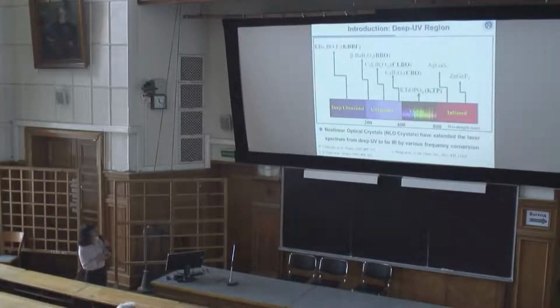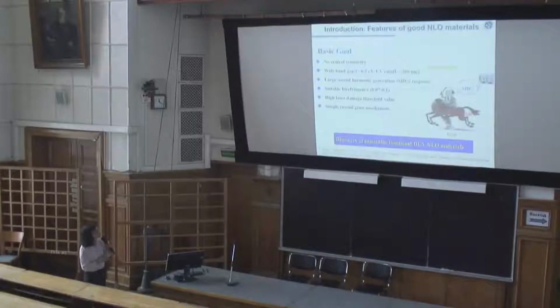Let's look at the wavelengths for these. For the UV and deep UV cutoff, in the deep UV region, almost all of them are borates. So we can say borate is very important. In the deep UV region, there is only one practical compound, KBBF. The requirement for the deep UV region is very stringent, because we should have a very large band gap, which means the UV cutoff should be short. Another thing is that we should have a large SHG response.